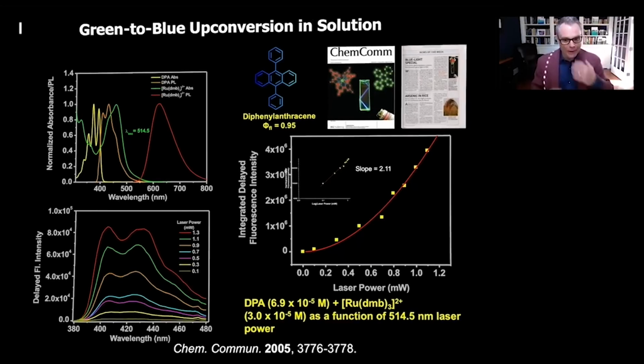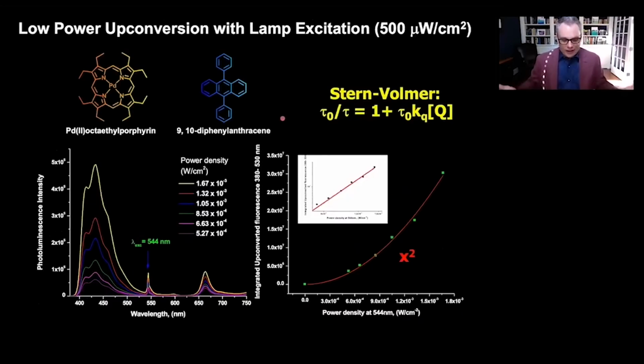So anyway, then you recognize the other pieces. The ruthenium trisbipyridine is a great sensitizer, and all the molecules in those classes are really good triplet sensitizers. The problem is, their lifetimes are really limited to about 1 to 2 to 3 microseconds, depending on the ligands you use. So that led us to recognize the fact that, well, if we use metalloporphyrins as triplet sensitizers, we can extend those lifetimes of the sensitizer into the hundreds of microseconds timescale.